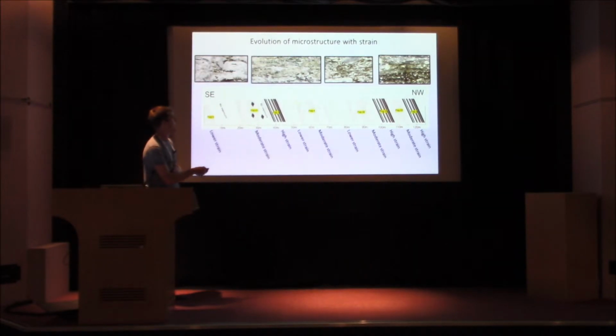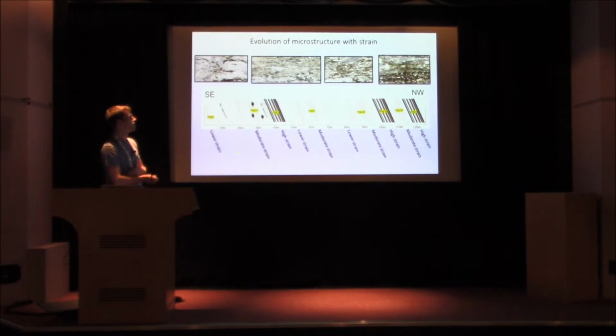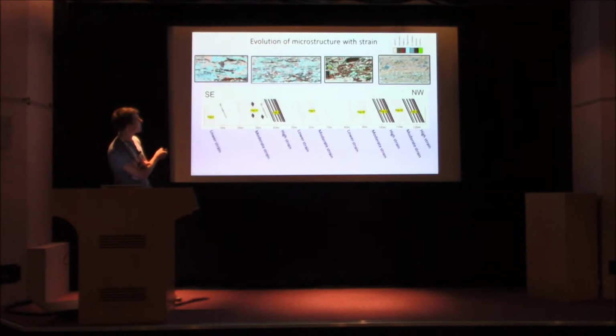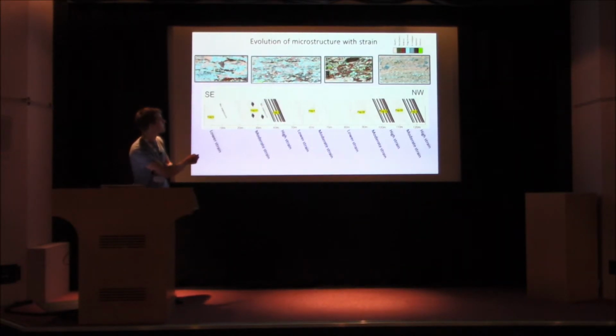If we look at the microstructural change across different degrees of shear, you can see from lower strain, the minerals to look at here are the darker ones, in this case the red and the green, they're the micas. You can see these are all the same rock type, but initially you have these quite large grains and large bands. Then this kind of lineation and interconnection becomes greater and greater as you move up strain until you get to the final very fine grain product.